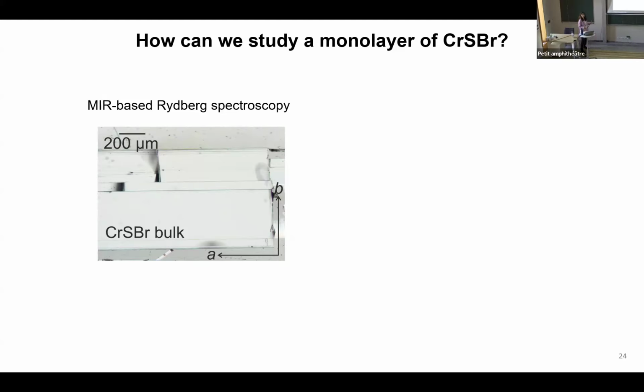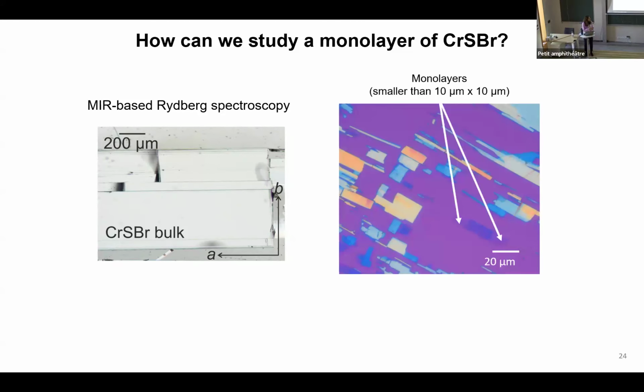However, when we exfoliate chromium sulfide bromide to achieve a few layers or a monolayer, we end up having flakes that are really tiny. The monolayer, specifically, as you see it as a grayish shade here, has a size which barely reaches 10 by 10 micron. So if I want to study it with our Rydberg mid-infrared spectroscopy and focus the mid-infrared radiation, its size would be much larger than the size of the monolayer.